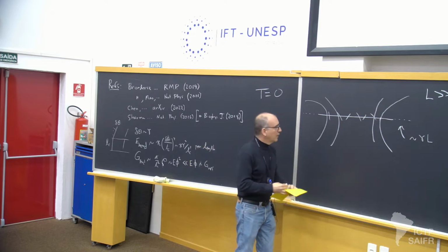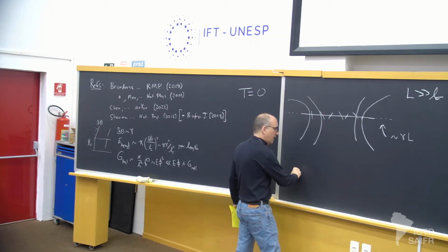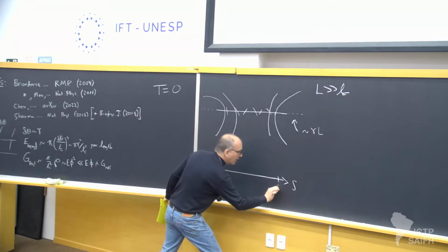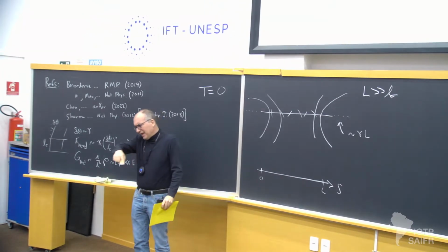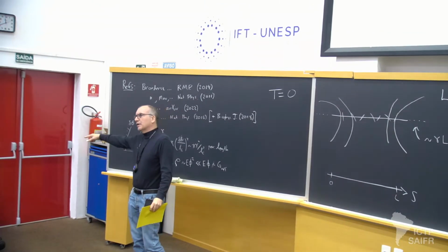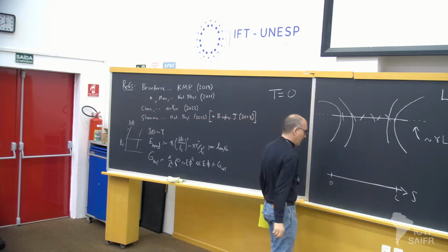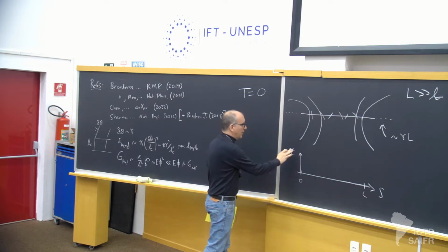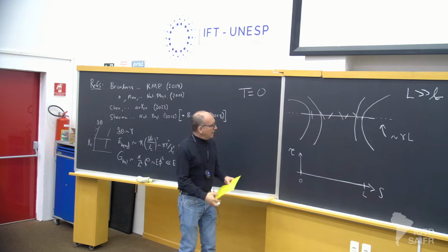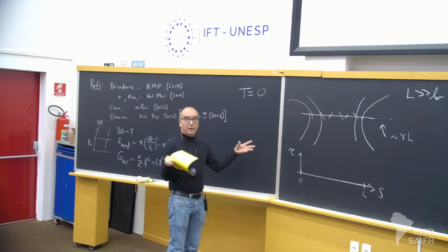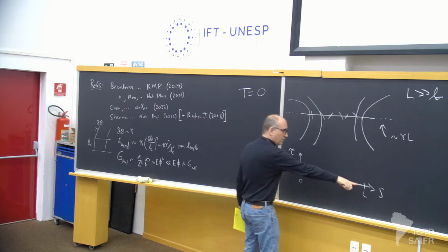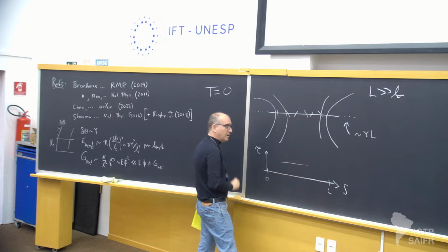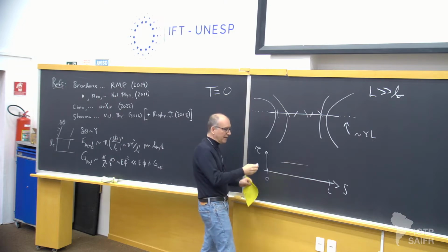So that ultimately means that the system will have to stretch if I go to high molecular weight. OK, so a more realistic picture is the following. I'll go down the arc length of the fiber from 0 to L, and just imagine labeling the relaxed, unstretched arc length. So that's the range of the fiber. You could imagine plotting the tension in the fiber. I'll call it tau. Well, in the fully non-affine case, if it can really fully relax the stretch, then of course this tension would be 0. But it won't be because of this mechanism. There will be some tension generated in the middle. It'll happen to be essentially flat in the high molecular weight limit.